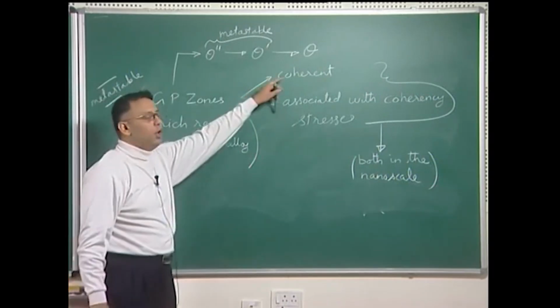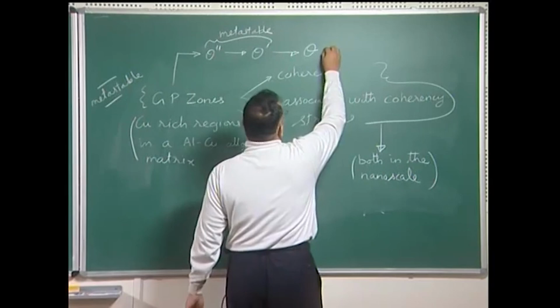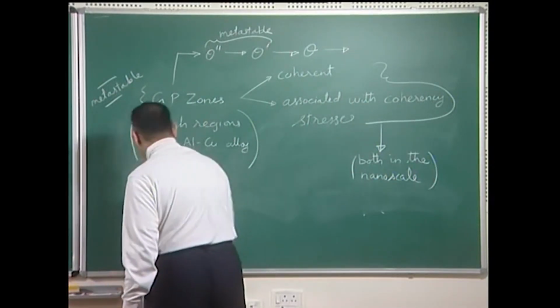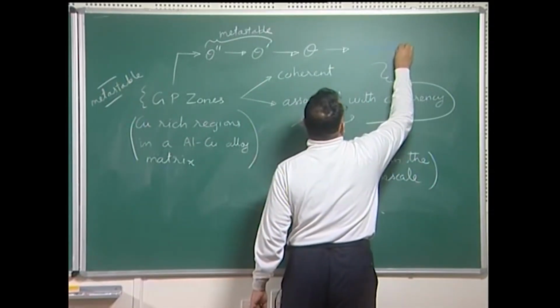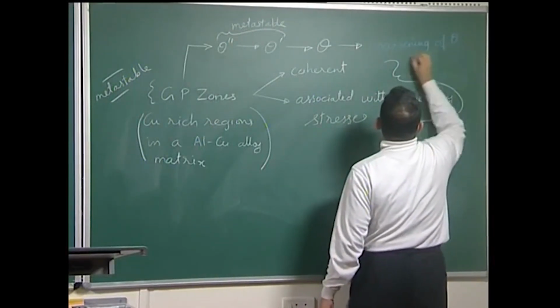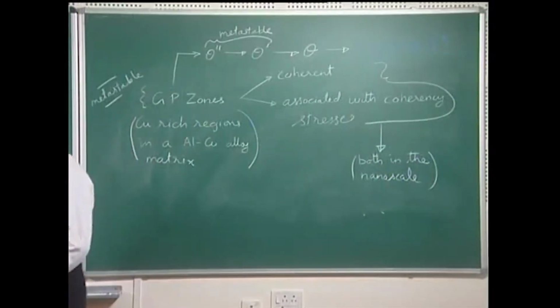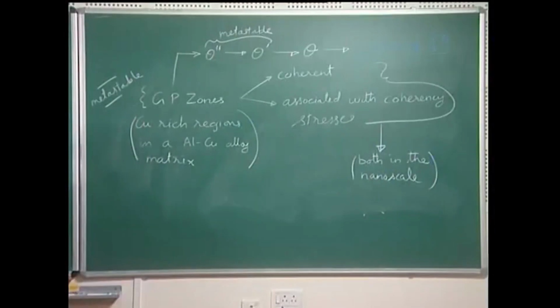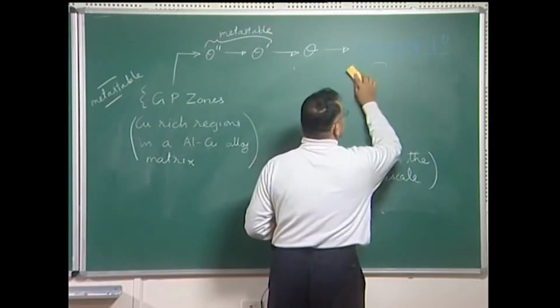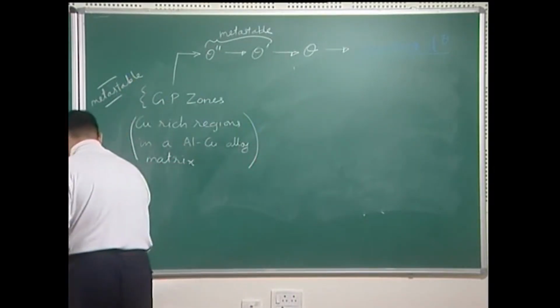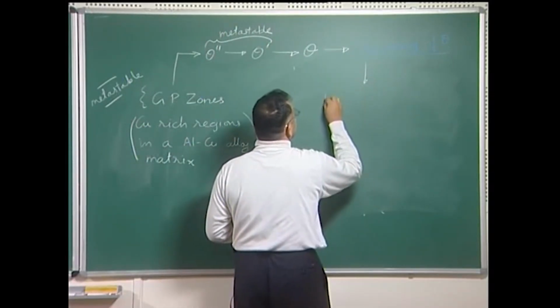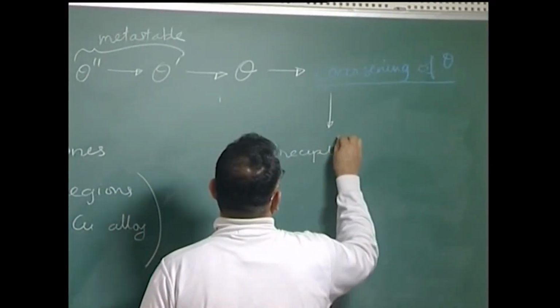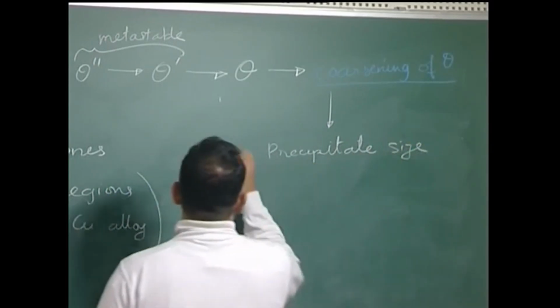And therefore, they will transform finally to the equilibrium phase theta, but it would not stop there, there will be coarsening of theta. In coarsening of theta, what will happen is that the larger sized precipitates of theta would actually grow at the expense of small size theta, and in the end the average particle size would increase, but the interparticle or the interprecipitate distance would decrease. And we are talking about the average precipitate size.